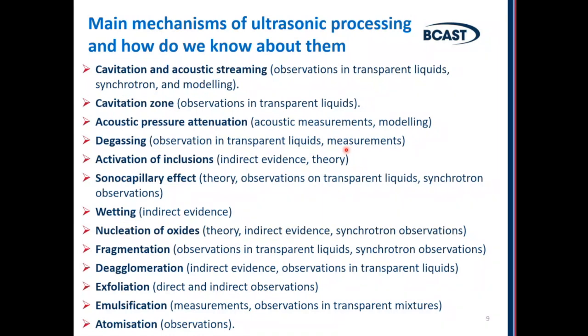Then there are phenomena which are associated with this cavitation. First of all is degassing. When these bubbles are formed, they're filled with gases which are dissolved in the liquid, and by that, a liquid can be degassed of the dissolved gases, for example, oxygen in water or hydrogen in aluminium, and that we can measure and observe in transparent liquids. Then cavitation activates inclusions, creating better wetting conditions on the surface of inclusions present in the melt, for example, oxides.